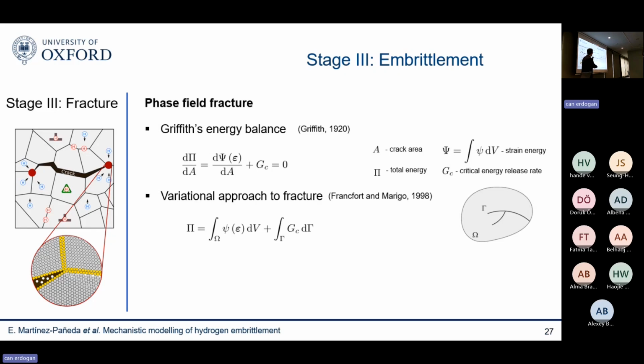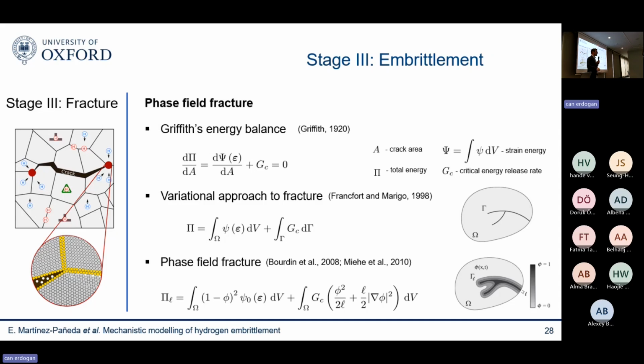And you can express this into a variational form. And then if you're able to minimize this functional, then you're able to predict the evolution of cracks as an exchange between the stored energy and the fracture energy. But this is tricky because you don't know where your crack lies. So here's where you make use of a phase field to enable the regularization of this functional and be able to predict the evolution of cracks. Again, as an exchange between fracture energy and stored energy in agreement with thermodynamics.